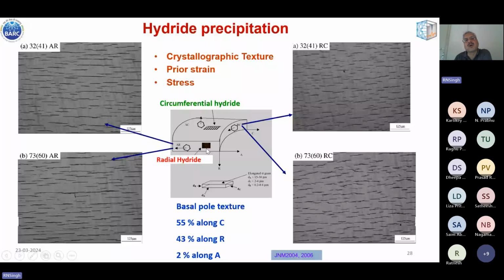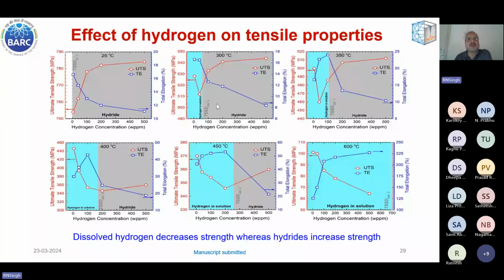And this radial hydride is normal to hoop stress. So that's why it's in red color. It is most deleterious. However, the circumferential hydride, even though it is a hydride, is not that deleterious because its major dimension is parallel to hoop stress. So it doesn't cause significant embrittlement. The effect of hydrogen on tensile property is shown over here.